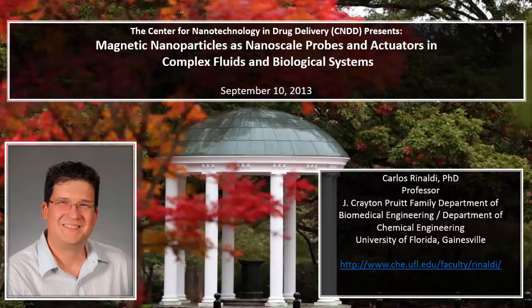And I'm going to show you that this works. In terms of how versatile a technique this is, this shows the location of the peak frequency as a function of medium viscosity for different particle sizes, for commercially available instruments you can use to make these measurements. And the point I want to make here is that you can think of using probes of a wide variety of sizes, between 10 nanometers and 1,000 nanometers. So you can really look at the probe size dependence of the mechanical properties of a complex fluid.